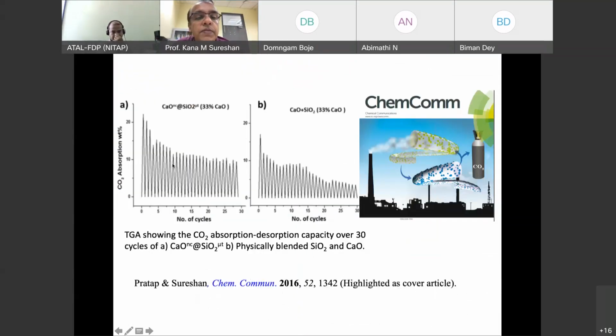We have used this material for carbon dioxide absorption, and it has about 33% of calcium oxide on silica. This is the first absorption, about 23% by weight. Then it slightly reduces in the next cycle, slightly reduces, and it is stable at about 12 to 13% over 30 cycles. This is the 30th cycle. You can still continue a number of times. So more than 10, 12 percent by weight it can absorb, and you can redo it.